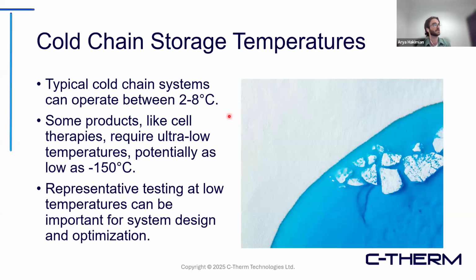One of the points I wanted to make here is that in cold chain storage, there is a variety of temperature conditions that may need to be met. Looking into it, many just simply require like a 2 to 8 degrees Celsius range. So kind of on the lower end, below your room temperature, but not quite into that cryo point yet. But again, some of the more specialized devices in cold chain storage, for cell therapies, for example, are noted to require temperatures as low as minus 150 C. So again, taking your materials and testing them under that temperature point of interest can be quite important.